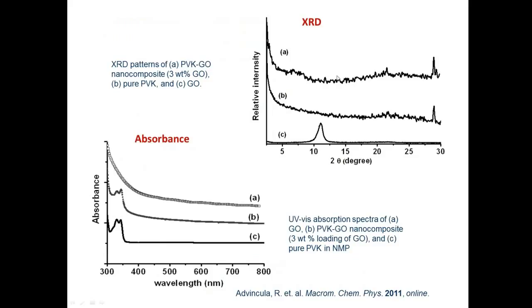Again, from XRD and absorbance measurements, in this case we have the graphene oxide and the complex graphene oxide with PVK. Here we can see that the graphene oxide shows a high degree of periodicity, which is lost by dispersing it with the PVK. On the other hand, the absorbance measurement shows that the carbazole group present in the material shows absorption near the UV visible region, or towards the UV. The graphene oxide itself does not have any absorbance in the visible region.